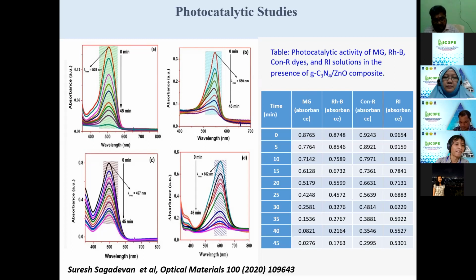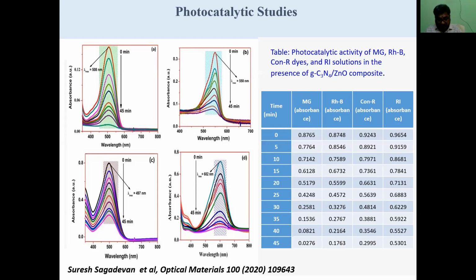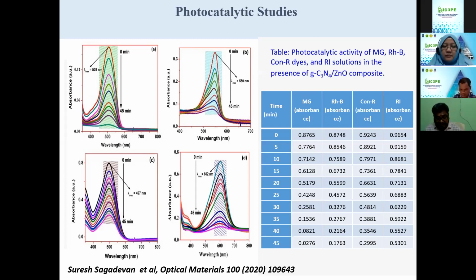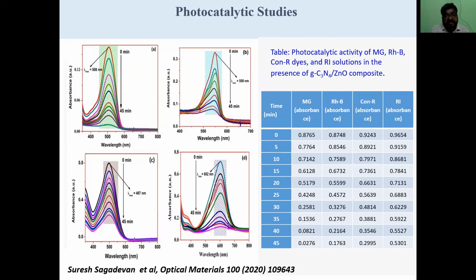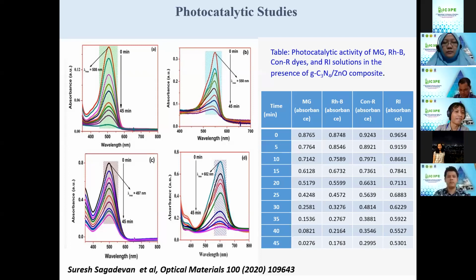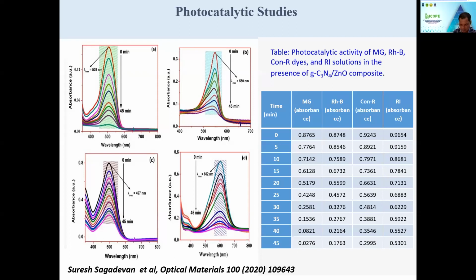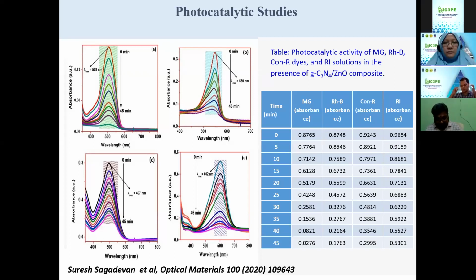There has been significant photocatalytic activity observed for the graphitic carbon nitride with zinc oxide composite, and the respective efficiencies are also tabulated here. From the analysis, we can observe that the composite has activity against all the dyes and solutions tested, though this activity reduces with the increase in time. This can be due to the loss in the number of active catalytic sites. Also, among all the reactants tested, we observed the highest absorption for this RI solution. RI means red ink solution, represented by figure D, 602 nanometer. This is the efficiency.